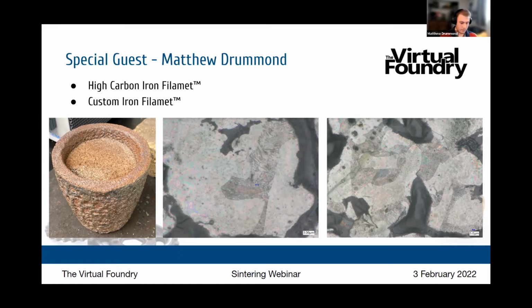And these are kind of rusty now, but I polished a couple samples, and you'll even see one sample is smaller than the other. The sample that was closest to the side that was really burnt, really sintered and underneath the coil, that's actually the smaller part. So that was something I noticed, was the parts that were closer to the coil and closer to that hotter side did shrink more. I'm not sure if I've got another slide there or not, Tricia.